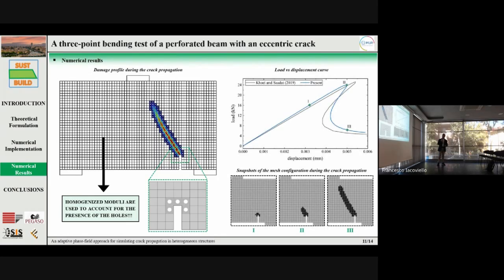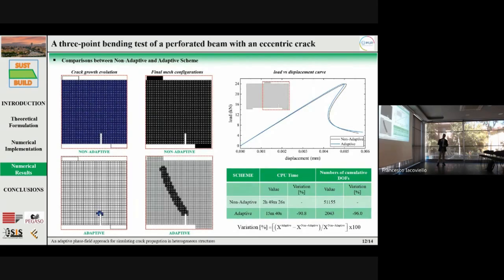It's important to say that homogenized moduli are used in the macro elements to account for the presence of the hole. Also in this case, a comparison in terms of load versus displacement of the midpoint of the beam between the present method and the numerical results provided by Khoei and Saadat is reported. And also in this case, the obtained curve is in good agreement with the results taken as a reference. Here we can see instead the snapshot of the mesh configuration during the crack propagation.